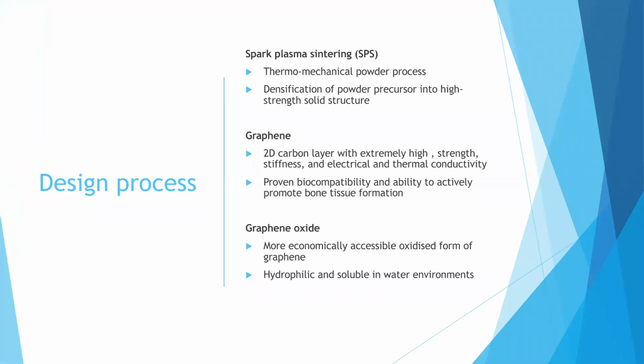The three main factors at play in designing our product are spark plasma sintering, graphene, and graphene oxide. Spark plasma sintering is a novel thermomechanical powder processing technique based on pulsed electric current, material heating, and uniaxial pressure. This allows for sintering to be carried out at accelerated rates, which minimizes energy and time demands, and results in a material structure which retains its nano-sized grain structure, allowing for high strength.